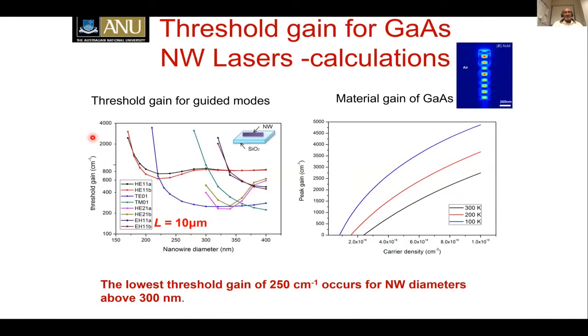He plots the threshold gain for lasing as a function of the diameter of the nanowire, for a nanowire about 10 microns long. You can see that the smallest threshold gain for lasing is for nanowires which are about 250 to 300 nanometers. In fact, if you use smaller diameter nanowires, the threshold gain for lasing is so high that before they start lasing, you start creating a lot of damage in these nanowires. He also plotted the peak gain as a function of the carrier density, and you can see the nice threshold-like behavior. Above a certain carrier density, lasing starts taking place, and the threshold carrier density also depends on the temperature of the device.